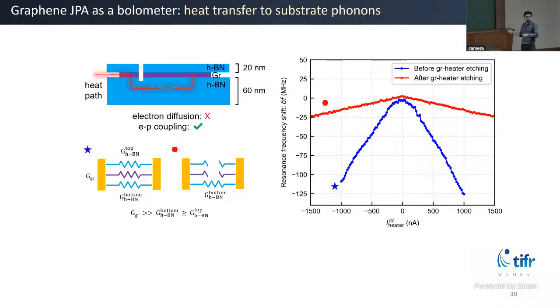The heat has no path to go to the other part of the device without going through the substrate phonon. So that data I'm showing you here is the resonance frequency shift as a function of heating. The blue curve is when there is no etching, so these three channels are activated, like the substrate phonon, the graphene all together.